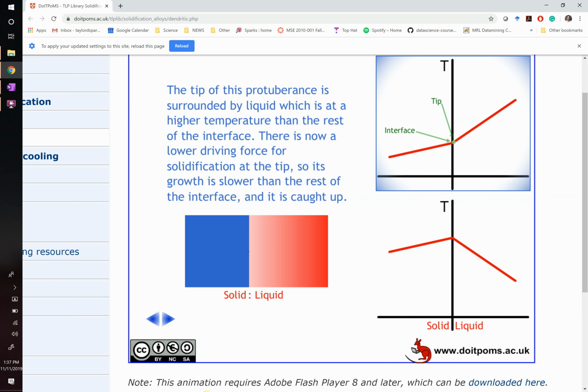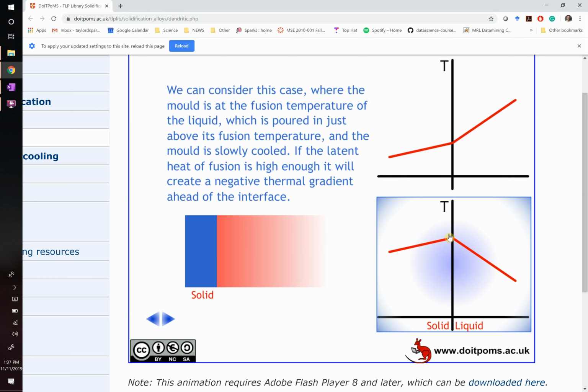Now, the other scenario is this. In this case, you heated your crucible up quite hot, and your material is such that as it solidifies, it takes energy, which is most things. Most things, as they solidify, it requires energy. That's why steam burns are so bad. The steam burns and it has to take energy. Oh, other way around, sorry. It releases energy, so it's going to be cooling itself off as it solidifies. So that leads to a temperature gradient where your crucible is relatively hot, but your liquid's less hot as it solidifies.